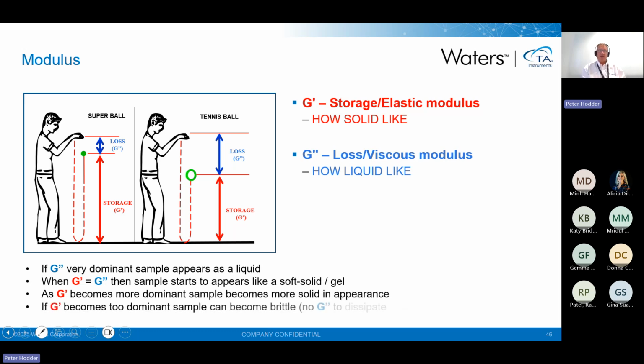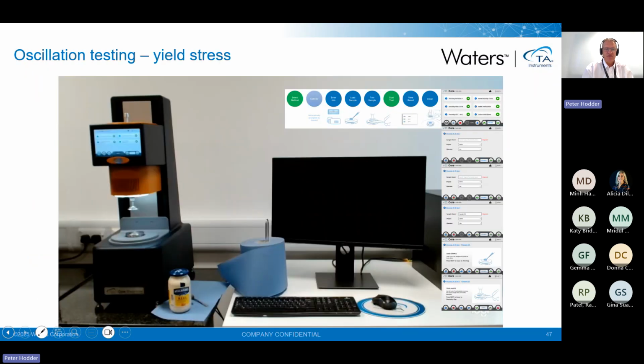If they're about 50-50, then they act like a soft, solid gel. And if you've got G prime becoming dominant, then the sample will behave like a solid and stay put. If it gets too dominant, it could actually become brittle. So again, the DHR itself can be used to do similar testing, but in this case, as the video shows.